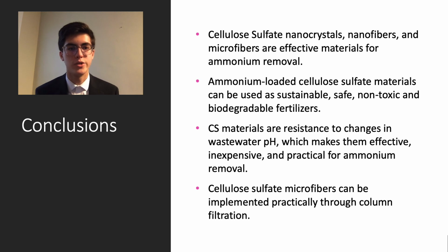The main conclusions of this study are that cellulose sulfate nanocrystals, nanofibers, and microfibers are effective materials for ammonium removal, that ammonium-loaded cellulose sulfate materials can be used as sustainable, safe, non-toxic, and biodegradable fertilizers, and that cellulose sulfate materials are resistant to changes in wastewater pH, which makes them effective, inexpensive, and practical for ammonium removal. Additionally, it's important to note that cellulose sulfate microfibers can be implemented practically through column filtration, and potentially nanofibers also if you were to implement something like a fluidized bed.